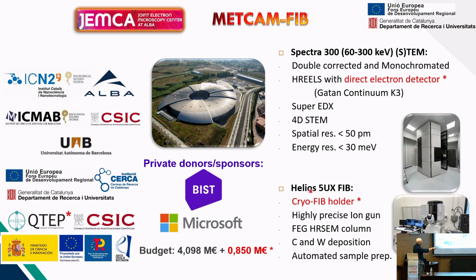And then this is the first microscope for quantum physical sciences or materials science for physics, also for chemistry, of course, but it's not for in situ, this one. The characteristics: it is a double corrected microscope, can work in TEM mode and STEM mode. In both cases, you have 50 picometers resolution, more or less. In STEM, you can go down to 45, 40 picometers. Then a super EDX, which means that you have many detectors around the sample and you can detect all the EDX that are around. 4D STEM, which is this new technique in which you can calculate the momentum of the electron. So this is really funny.